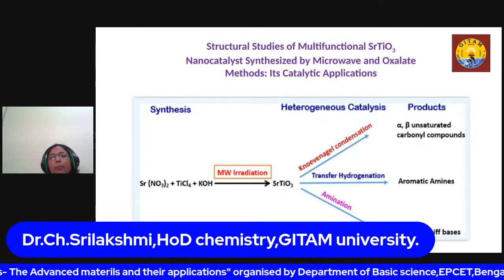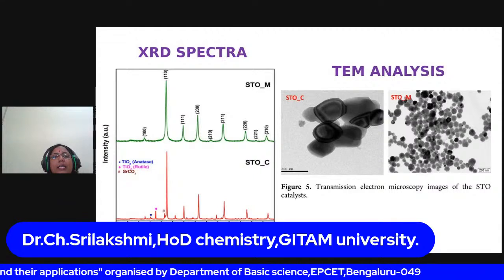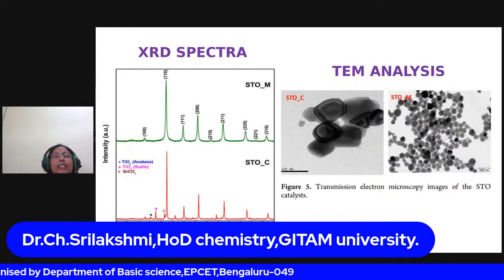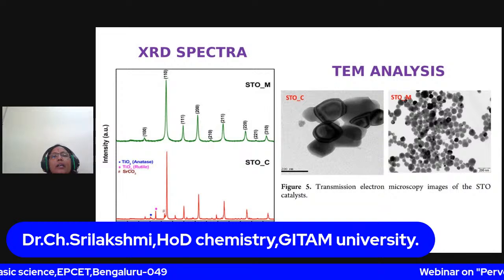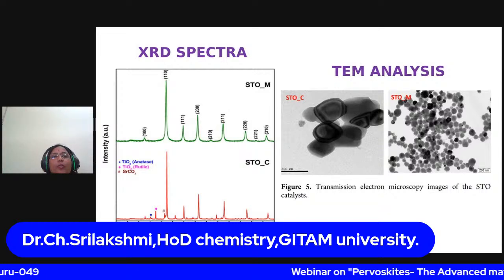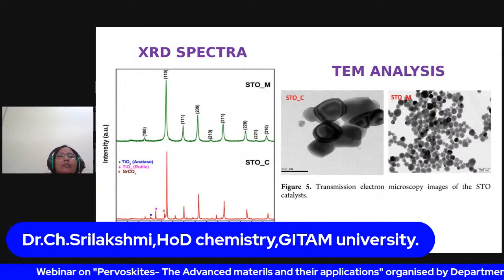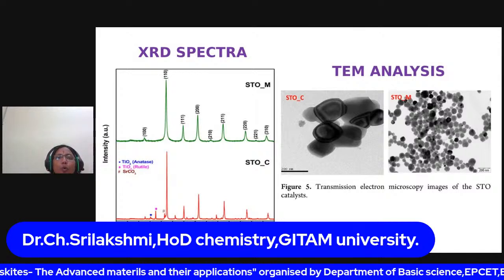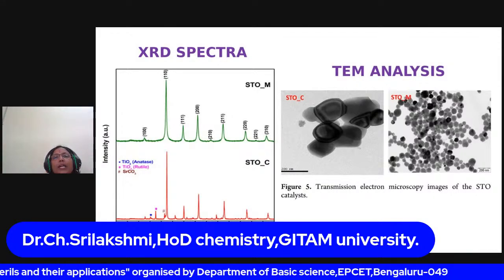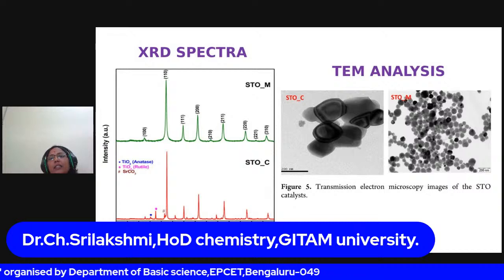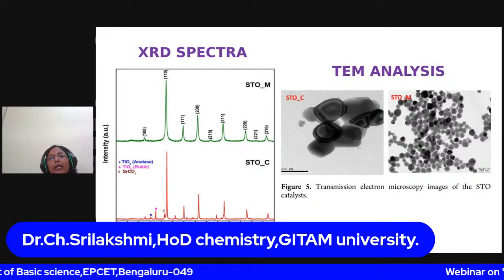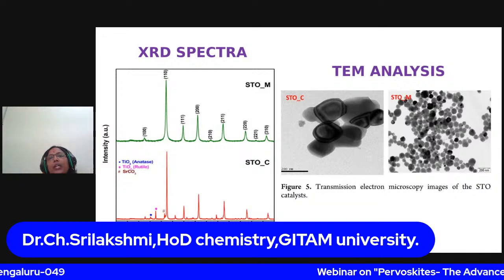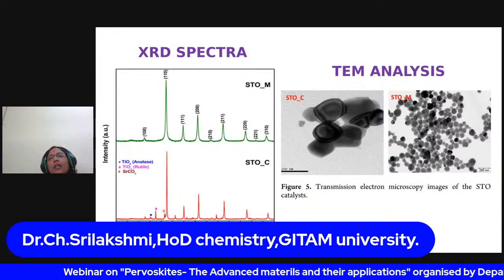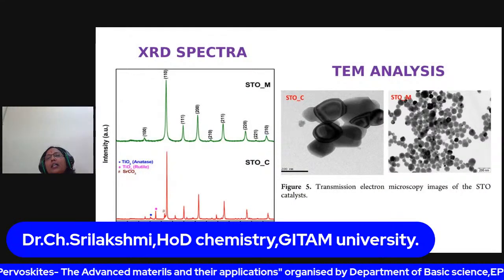This is published in ACS Omega. As you can see, this is the XRD of conventionally synthesized strontium titanate by the oxalate method, and this is the microwave method. You can see we get pure compounds with the microwave synthesis method, and both compounds exhibit the cubic strontium titanate phase. And here is the TEM analysis. Large cubic nanoparticles are observed in the conventionally synthesized strontium titanate, whereas in the microwave one you can see nicely porous small particles uniformly dispersed through the sample.